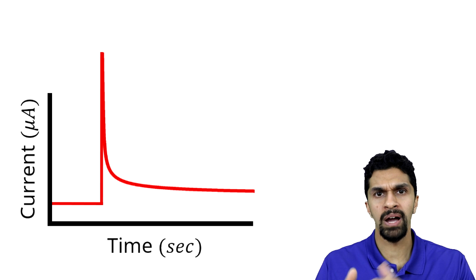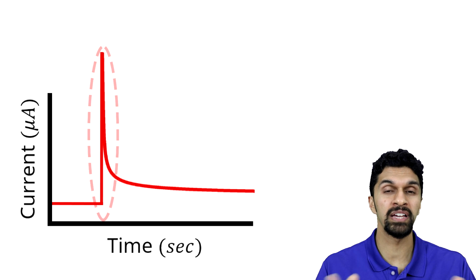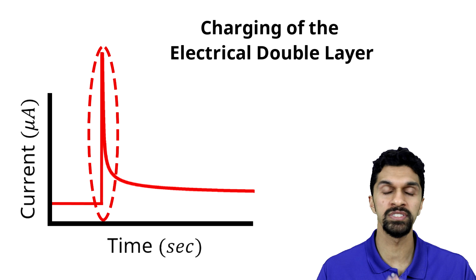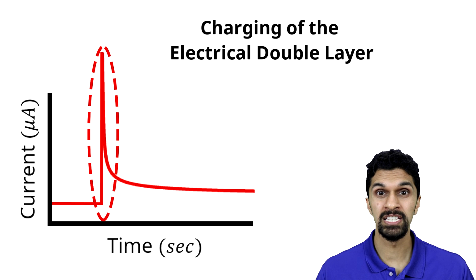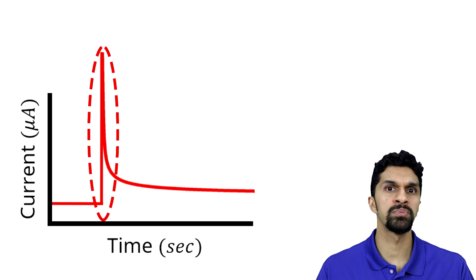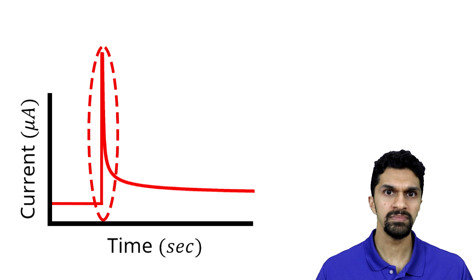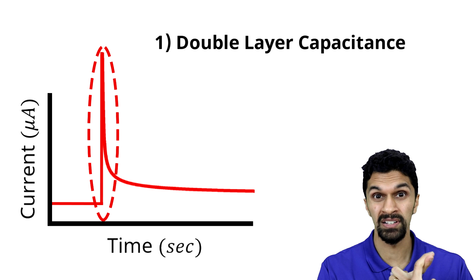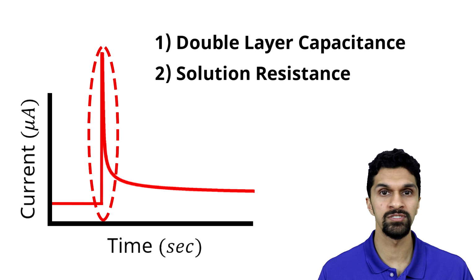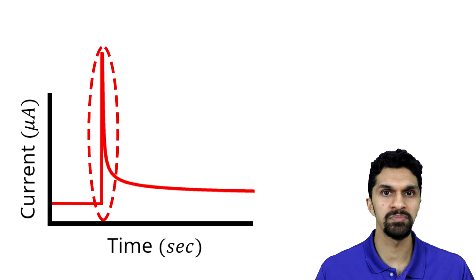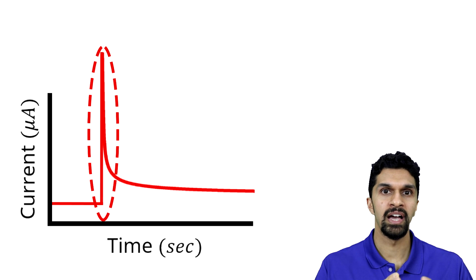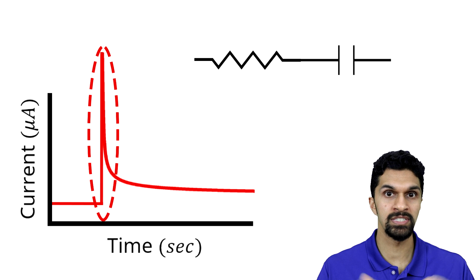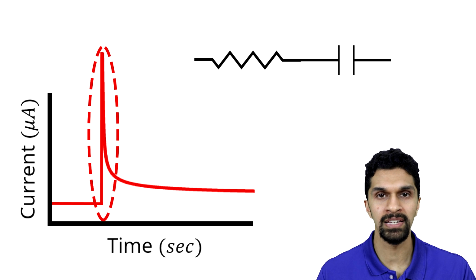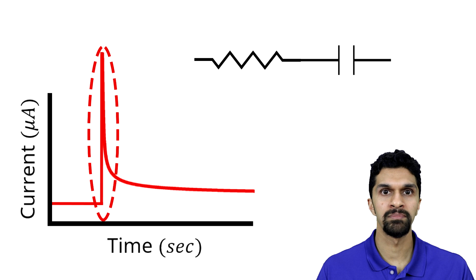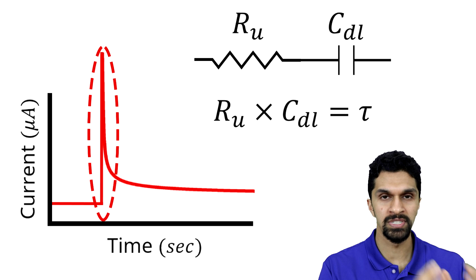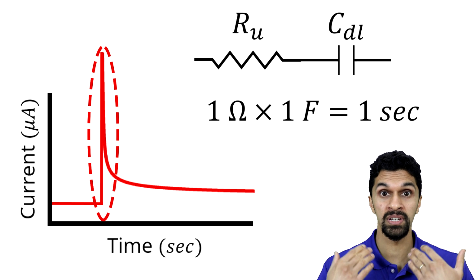Now, going back to our chronoamperometry experiment, this initial spike in the current, part of it is due to the charging of the electrical double layer, and that charging is pretty fast. The speed at which the electrical double layer charges is actually based on the capacitance of the double layer as well as the uncompensated solution resistance. We can model this based on electronics and circuitry as a resistor and a capacitor in series. And in this circuit, the time it takes to charge the capacitor is based on the RC time constant. The resistance times the capacitance gives us units of time.